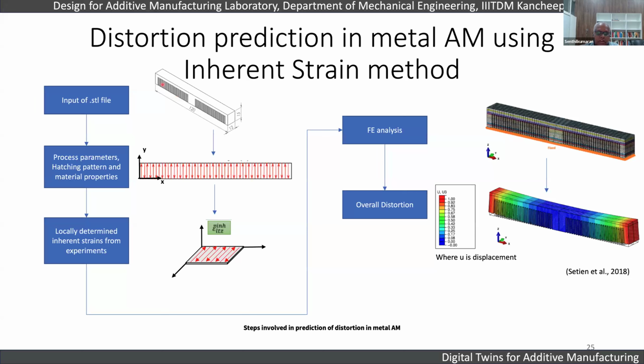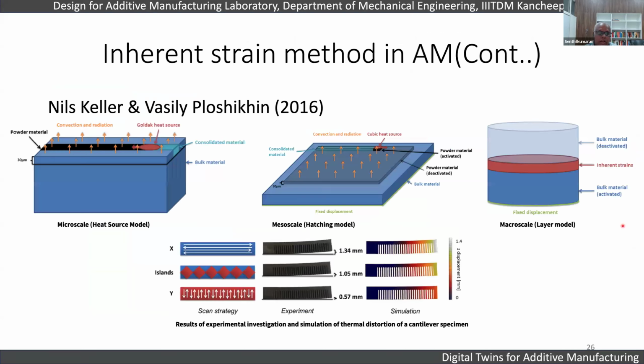So then it is going to basically deform like this. You can see the deformation happened because of the relief, residual stress is relieved. So you measure those strains, and then you solve the inverse problem to get the inherent strain from the measured strain value. For that, Nils Keller has developed a very interesting methodology. In fact, his software is also commercialized.